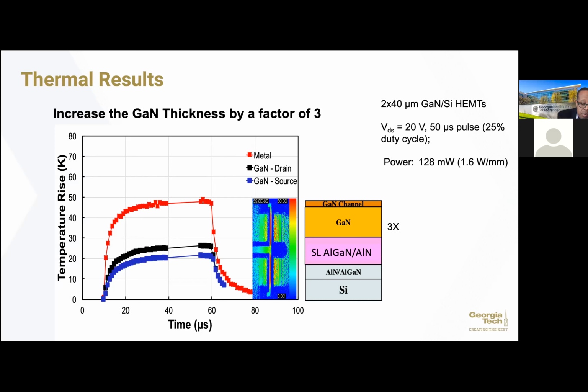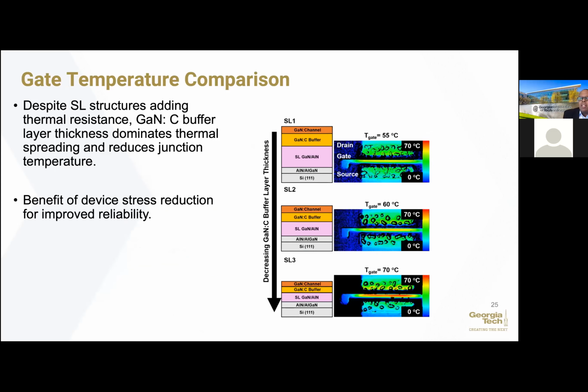Plus, this also helps you if you want to move more into power devices and not just RF with these particular structures. So here's just a summary. It was an interesting mix of various parameters. I have a very thick superlattice structure, and I have gallium nitride on top of this structure. You can see that this structure actually has the lowest temperature. Then if I were to take this gallium nitride, thin it down, as well as thin down the superlattice structure, I actually get a higher temperature. And so again, this just shows you that there are interesting co-design aspects that have to come into play when you start looking at how these structures will behave.